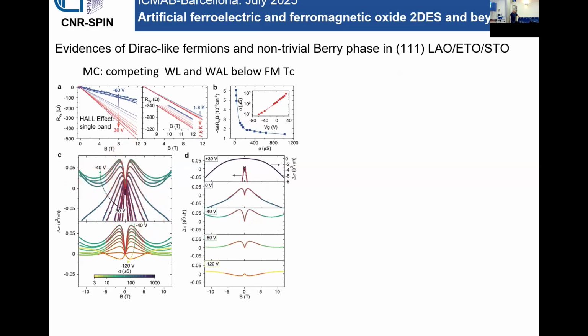very pronounced. And to fit this data, we should rely on a formula which is very simple and has actually been worked out for topological insulators with the magnetic gap or with a gap in general, where we have a contribution from weak localization and another one from weak anti-localization. And this formula works quite nicely. You can fit the data very well. And so this is the first thing that suggests our system probably belongs to this category of type 2 semi-metal, and everything is related to the non-trivial Berry phase.